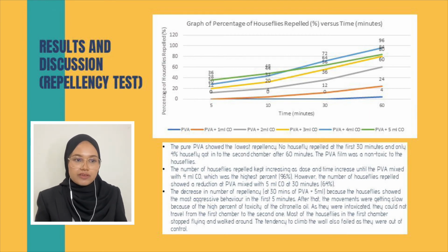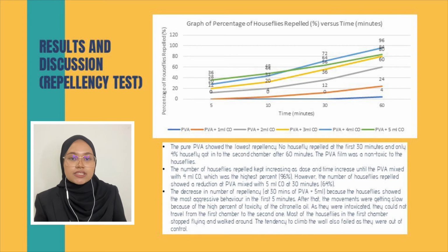The repellency test can be seen in the graph. For the pure PVA film, there is no housefly repelled for the first 30 minutes, but there is 4% repellency at 60 minutes. And then the number of houseflies repelled kept increasing as dose and time increased until the PVA mixed with 4 ml of CO, which was the highest rate with 96%.